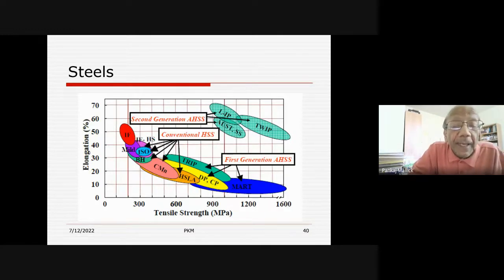So as I mentioned, the steel companies are making better, higher strength steels. But the higher the tensile strength, the lower is the elongation. This is sometimes called a banana chart because the chart looks like a banana, but it divides the steels into different segments. So the low carbon steels would be on the left side of this diagram, and the very high strength steels are on the right side. The higher the strength, the lower is the elongation, and therefore the lower is the formability. It becomes much more difficult to produce the shapes with very high strength steels.